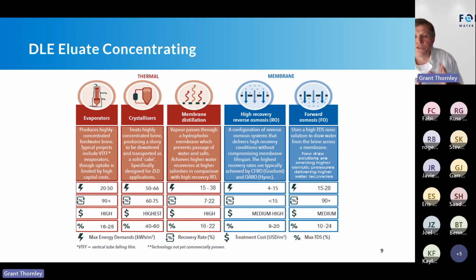It's thermal evaporators, so it's using a heat source to pressurize and heat up a bulk fluid in which I'm going to drive water off through a distillate and then cool that. By driving that water off, that's how I'm going to concentrate. Evaporators have been around for a very long time and are well understood, but the challenge is that they have a high energy component. And on the OpEx side, because of the high temperatures, high pressures, and the very high fouling and corrosive environments, they have a very, very high maintenance or OpEx component. So not only on the CapEx, but the OpEx is significant on them.